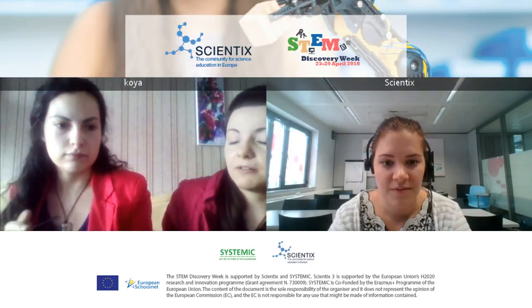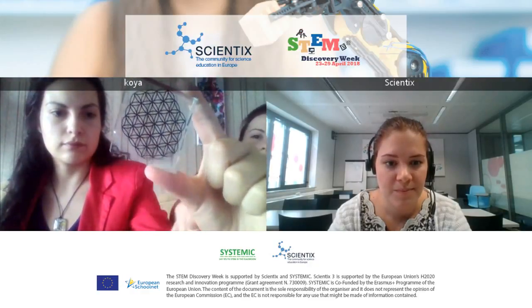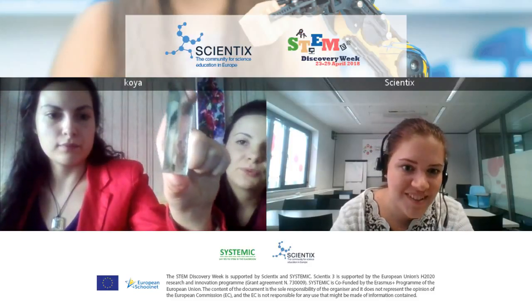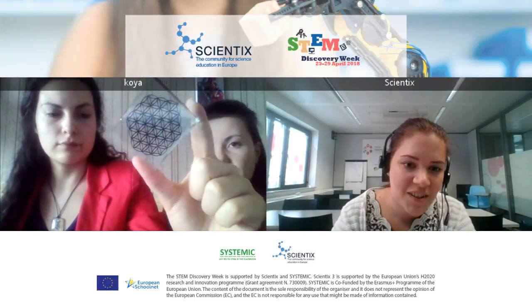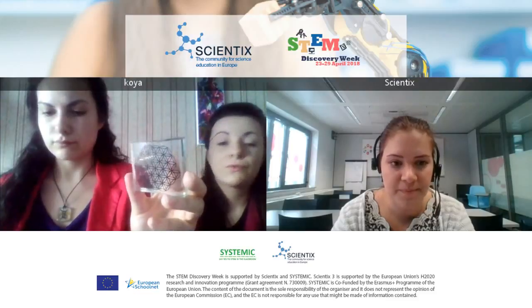The other method which they're going through right now is called decals or copies, which is on flat glass. They put a special ink on a special paper. They can print different shapes, scratches, or pictures which every author has made. And when you go through fusing again for about 24 hours, but at a lower temperature, around 500 degrees Celsius, they remain on the glass and remain durable.